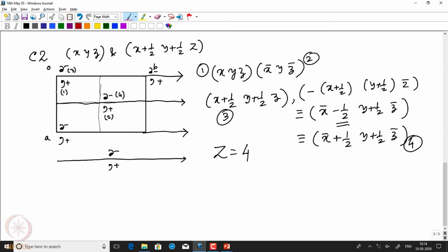They are related by a 2-1 screw passing through 1/4 along A and 3/4 along B. So this then completes the space group diagram for C2, which indicates that the presence of two parallel two-folds on a C-centered lattice gives rise to a 2-1 in between.